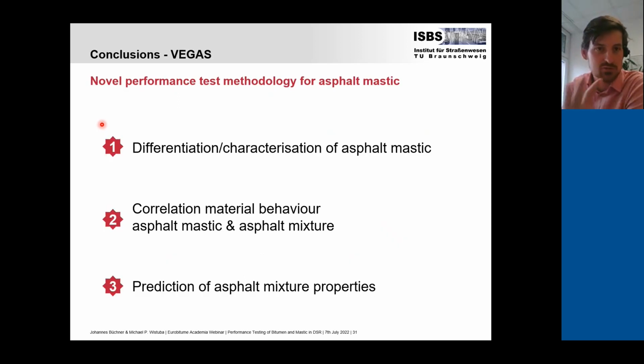So overall, conclusions for this project: it's a novel performance test methodology for asphalt mastic. There are three main outcomes. The first one is that a differentiation and characterization of asphalt mastic is possible. We can clearly see the influence of different binders, different fillers, and their influence on the mastic. We found a correlation of the material behavior for asphalt mastic and for asphalt mixture between both scales. And possibly also a prediction of asphalt mixture properties by only looking at the mastic, since there was a clear correlation between those results.